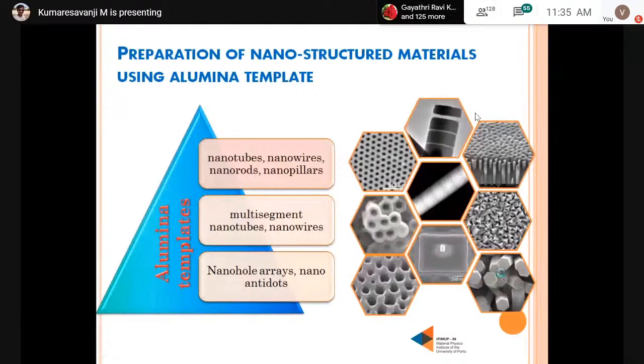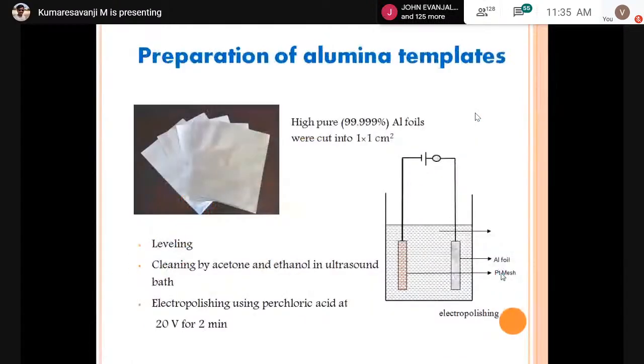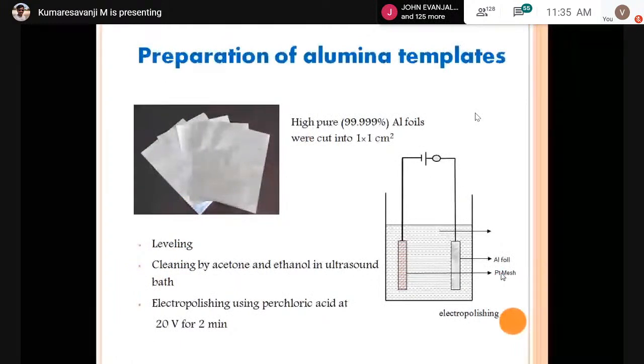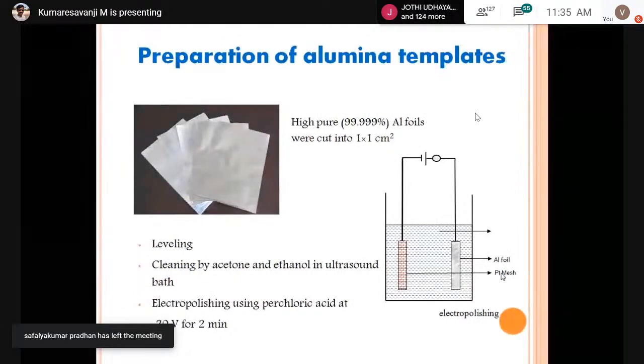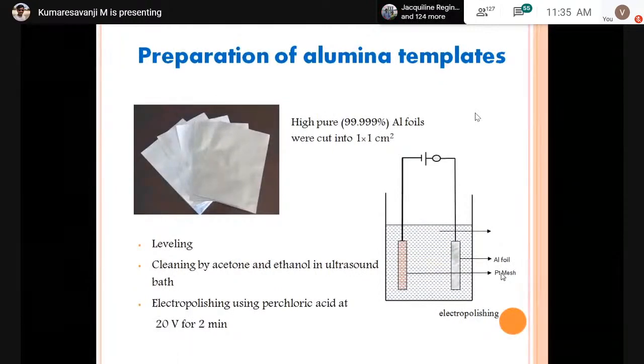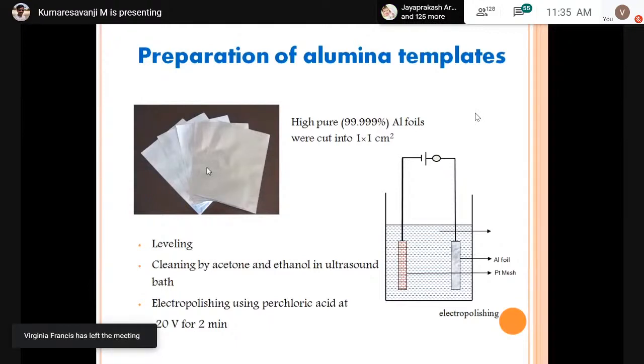So alumina template preparation is a very easy step. We need to do anodization. For this, first we take high pure aluminum foils that we cut into 1 by 1 centimeter squares. Then we do the leveling, because it comes by roll, right? So we just cut it, and then, because the aluminum is easily oxidized with the atmosphere, we need to first do the electropolishing. Before the electropolishing, we clean the aluminum foil with acetone and ethanol, and then we do the electropolishing using perchloric acid at 20 volts for 2 minutes.